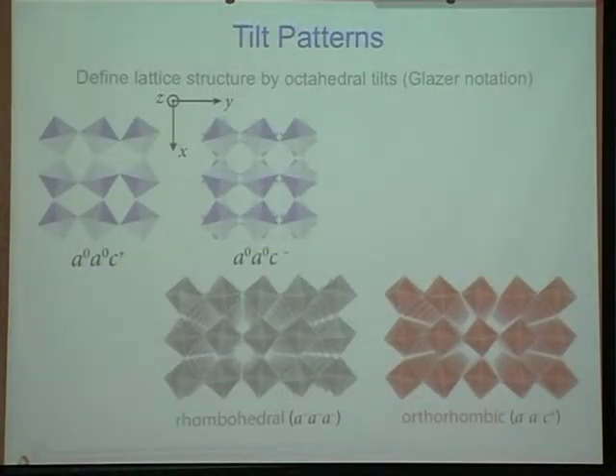So then we started to think a lot about the symmetry of these films. In particular, people talk a lot in terms of what's called Glazer notation. This is a way to basically take regular octahedra and concoct many different space groups by simply having rotations in 3 different directions, and those rotations can either be in phase or out of phase. So for example, in rhombohedral, they're out of phase in all 3 directions, and they're all A, which means they have the same magnitude. Whereas in orthorhombic, they're out of phase in 2 directions, but they're in phase along the c-axis. And so these have a very different rotational symmetry.